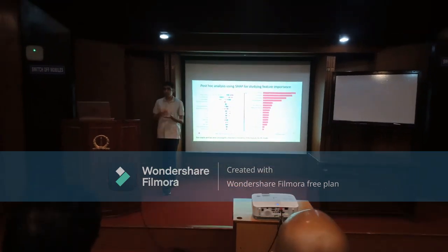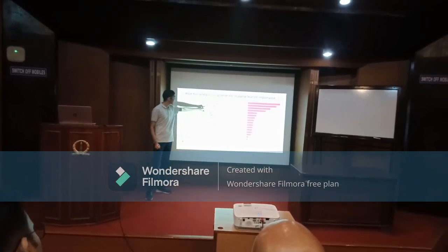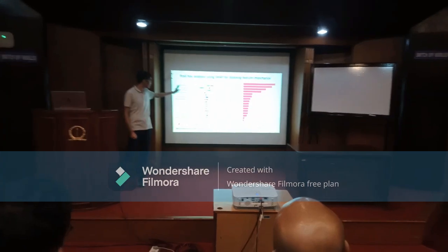So what this tells us is that if the value of this particular feature, scan velocity, which is the velocity at which the laser is moving, is high, then we can expect that the property value, which is our yield strength, will also be high. Similarly, for laser power, we can see that it's the inverse. If laser power is high, we get a lower property value. So, what could be the reason for this? Why is the model attributing a higher property value to higher scan velocity, but a lower property value to higher laser power?